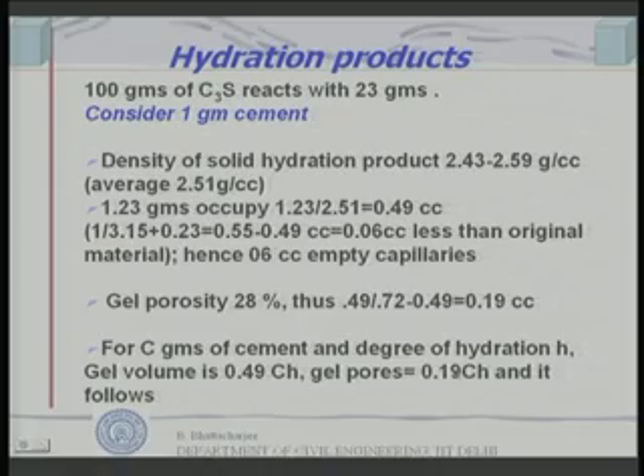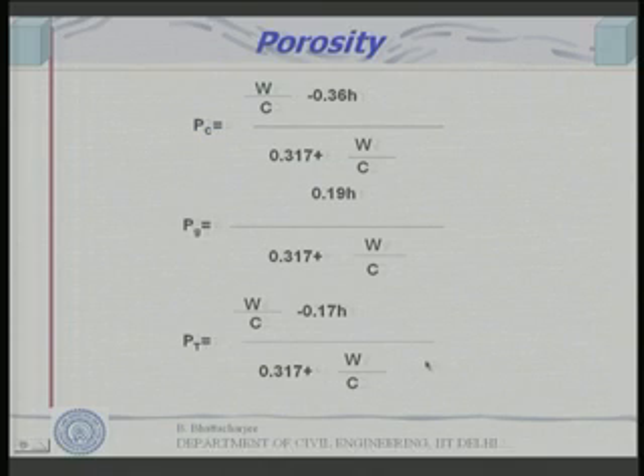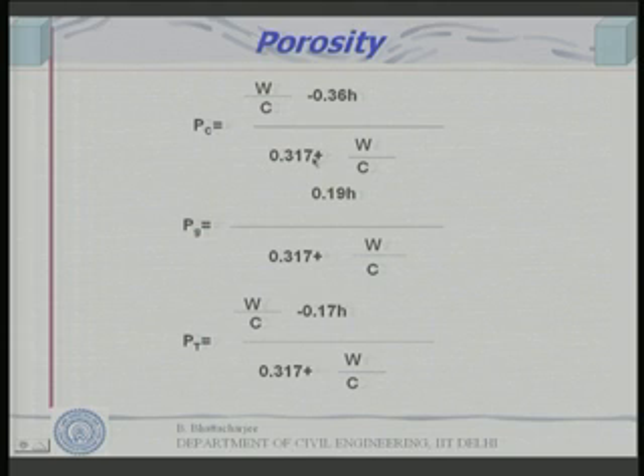Now, supposing I take C grams of cement and take the degree of hydration as H, my solid gel volume would be 0.49 Ch, and gel pores will be 0.19 Ch. It follows therefore that I can find the capillary porosity by subtracting from the original volume the volume of unhydrated cement, the volume of solid gel, and the volume of gel pores. What is the volume of capillary pores? Divided by the original volume, this results in capillary porosity, and the expression for capillary porosity is something like this.